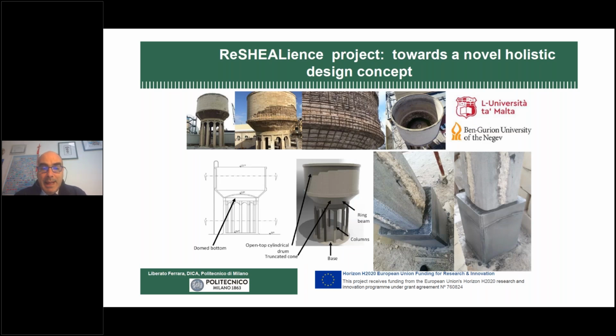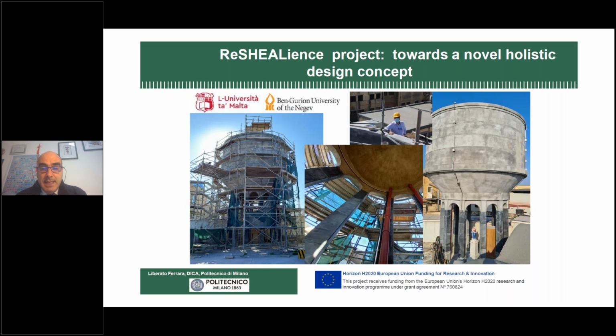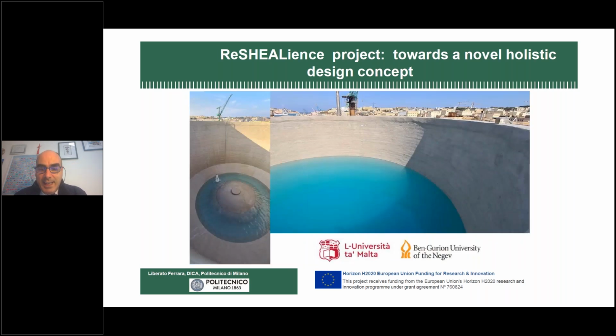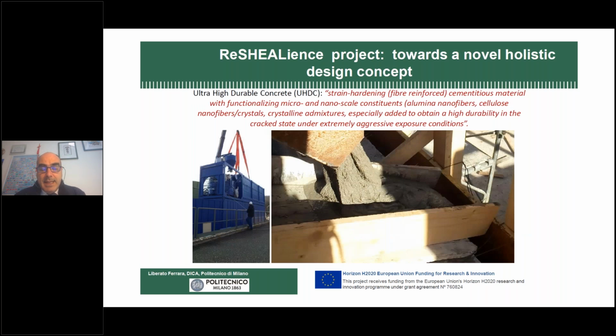And some images of the Malta pilot. This was an existing structure, a water tower, which was severely damaged, as you can see, and we retrofitted it, employing both ultra high durability concrete with dispersed fiber reinforcement, and for the drum with textile reinforcement. Some images of the finished structures. We were also able to go inside before filling it once again. These are some images of the load test made during filling, and now the structure is in use in the Valletta Harbor area.